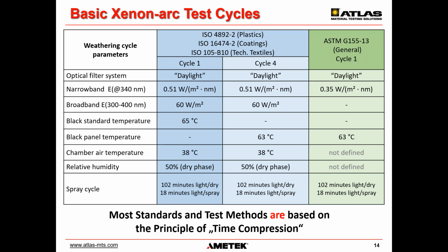Many basic test standards specify typical maximum values for the key testing parameters. For example, the 60 watt per square meter, which I just used in my quick calculation, is a typical maximum natural noon irradiance. 65 Celsius is a maximum temperature frequently occurring at noon in extreme climates such as Phoenix or Chennai. Measurement data of all these values and how the test methods are derived from the real world data is dealt with in other parts of that fundamentals of weathering series, in the outdoor part and also in the standard part. But here are some basic test cycles for plastics, coatings, and textiles, and ASTM G155 in general.